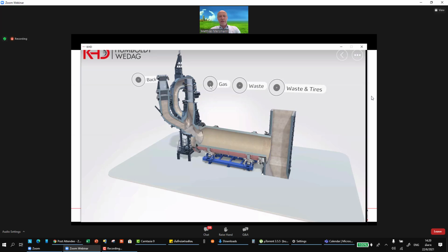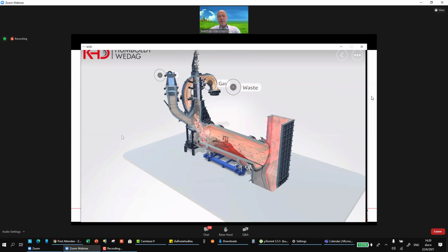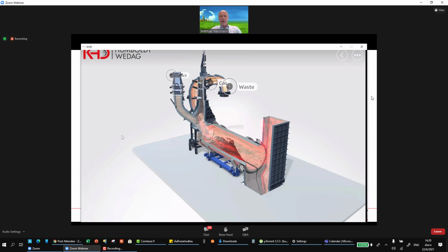You see the airflow coming from the tertiary air through the PyroRotor. And if I now start feeding material into it, you see that the alternative fuel forms a layer in the rotating kiln with surface renewal, constant surface renewal that makes the material accessible for the combustion. And in the end, the off gases are being mixed into the calciner riser, so that